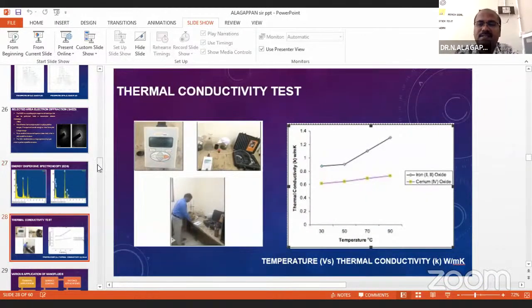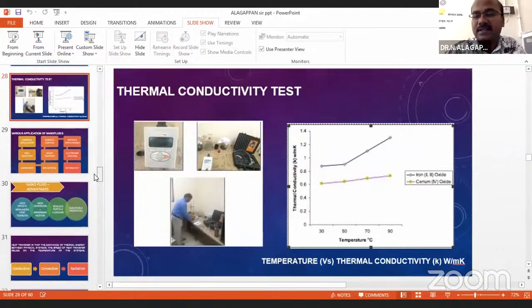Next is the thermal conductivity test. From the thermal conductivity test, we can identify how much heat transfer is possible with your nanofluid, because once you know the thermal conductivity, you know the efficiency of your particle. So regarding cerium, it goes up to 0.75, but for iron oxide, it goes beyond 1.2, which means the Fe3O4 is best when compared to CeO2 nanofluid. Next slide, sir.